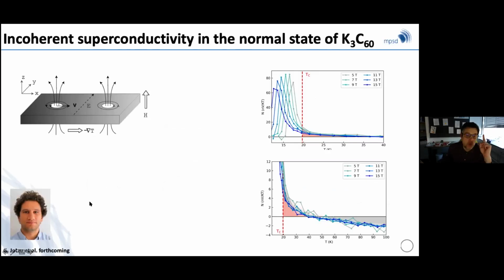And again, the first qualitative point that I should show you, after a lot of work, is what Gregor showed in the C60, which by the way is a three-dimensional system in which a superconducting Nernst effect was never characterized. This is unpublished data. What Gregor showed is that you have a very sizable Nernst effect at temperatures that are far in excess of TC. Depending on how you fit the negative quasi-particle contribution, it could be all the way up to 100 Kelvin, but certainly up to 50 or 60 Kelvin.